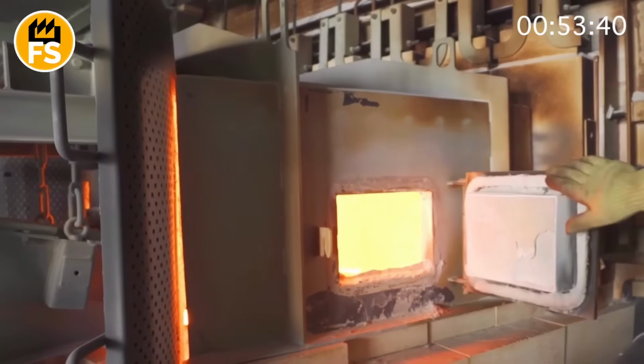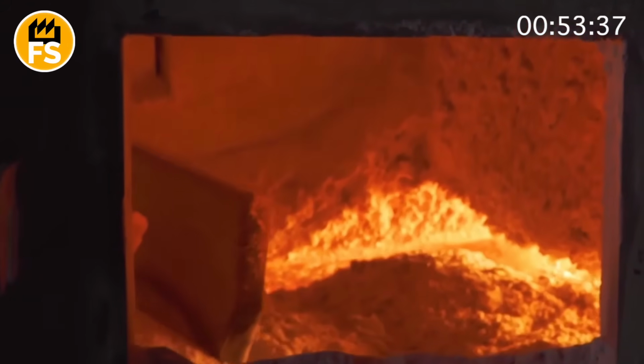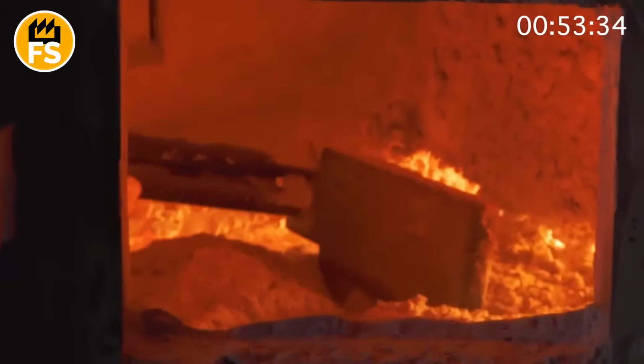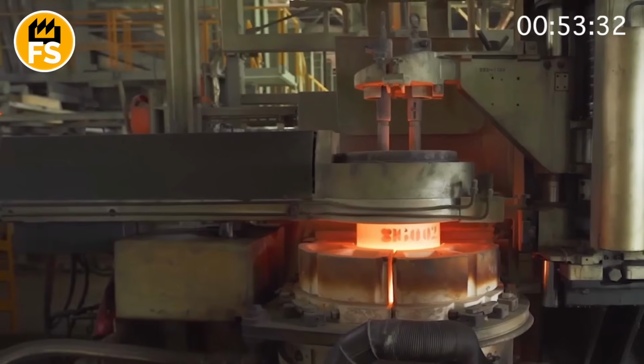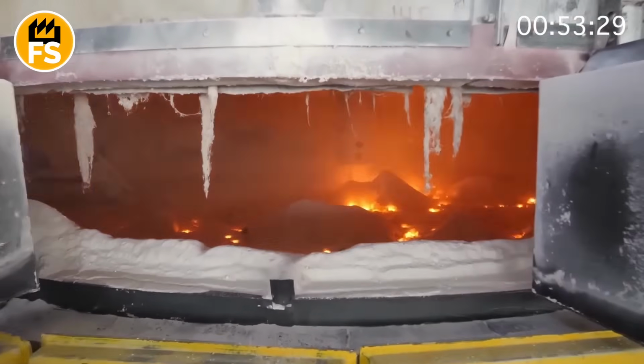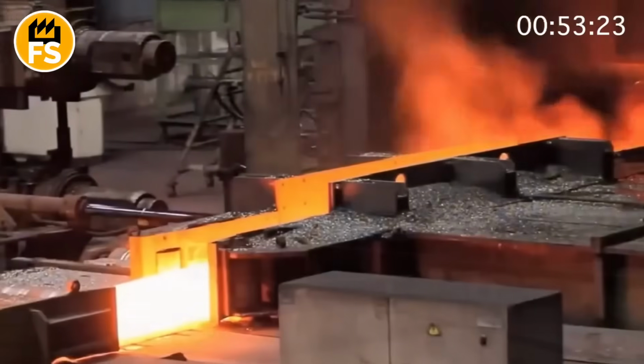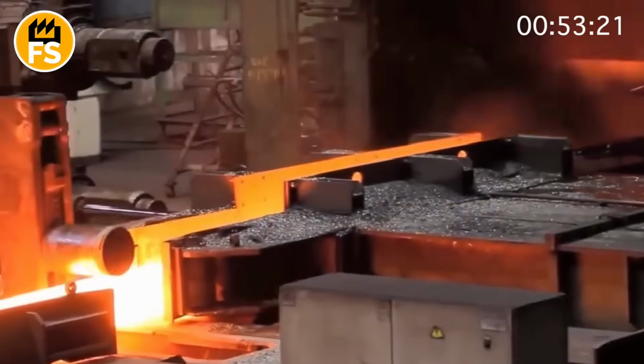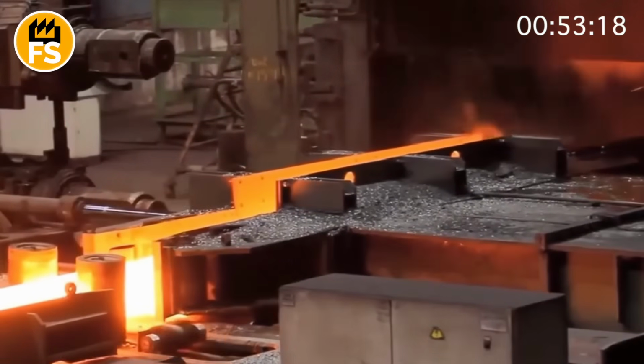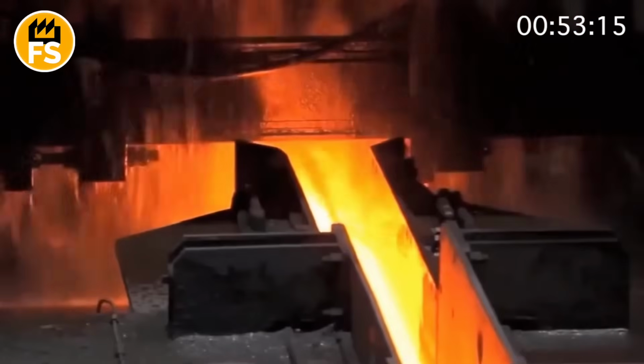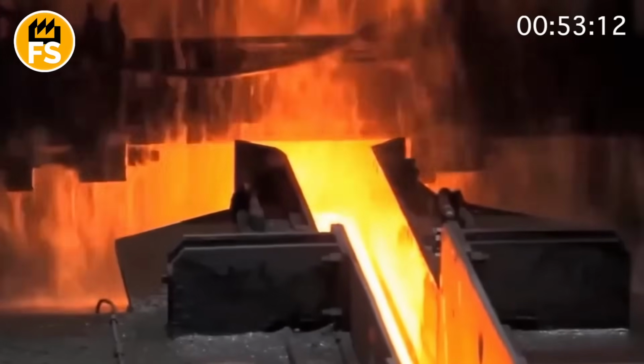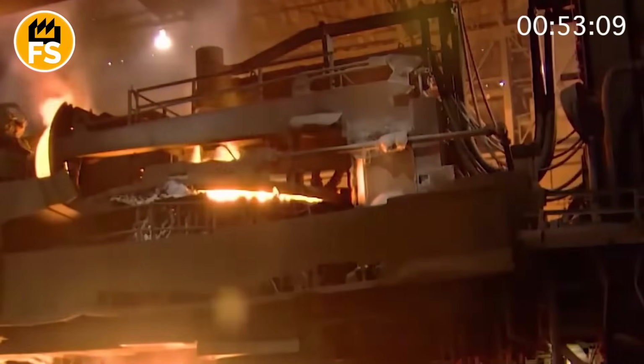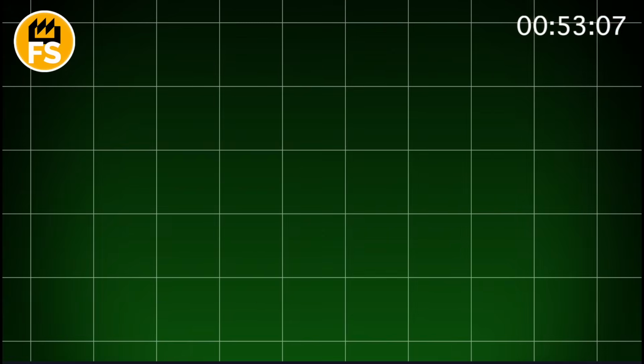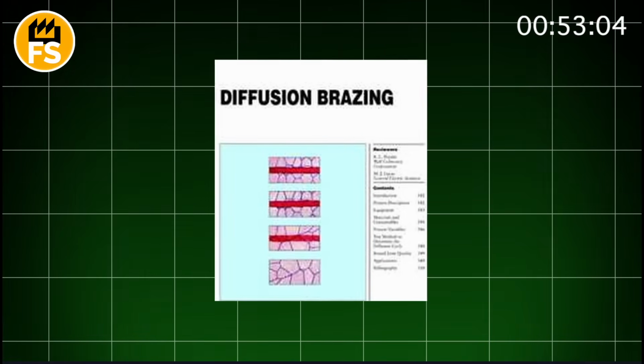Large, sealed like a vacuum capsule, it slowly swallows the blanks. Inside, an oxygen-free atmosphere, often with nitrogen or argon, to avoid oxidation. The temperature rises gradually to avoid creating stress in the metal. At its maximum, about 1,112 degrees Fahrenheit for aluminum, the filler metal begins to flow, but not boil. It fills the gaps, like liquid gold, penetrates the smallest crevices between the tubes and fins, binding everything together, like lava squeezing mountain rocks into a single block. This process is called diffusion brazing, extremely precise and uniform.